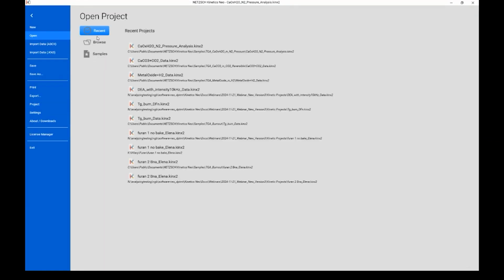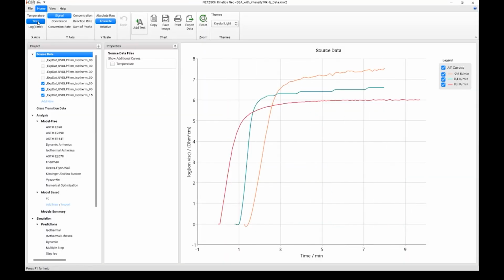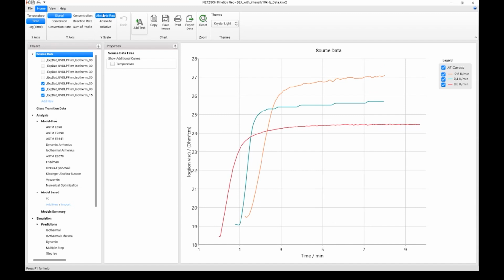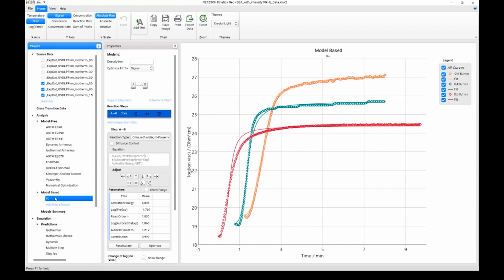Here we can open the data with DEA with intensity. Here is our data, measured data with log of ion viscosity. We have here the first kinetic model, which depends on temperature only and does not depend on other parameters. Here is the first part where we start our analysis.